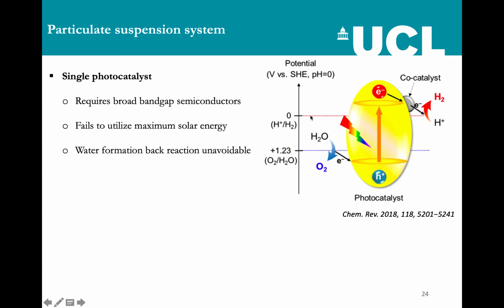For that, the theoretical minimum energy needed is 1.23 volt, but in reality any material has to have energy higher than 1.23 volt, because the system probably needs some overpotential to activate the water splitting. And mostly, for this single photocatalyst for the two half reactions, we always require broad bandgap semiconductors, meaning let's say 3 eV or 3.2 eV. Because of this higher bandgap, they can absorb only the UV light from the solar energy, not the visible light. And as I explained in the very beginning of the presentation, only 5% of the solar energy is in the UV region. So it fails to utilize the maximum solar energy, which is in the visible, 45%.